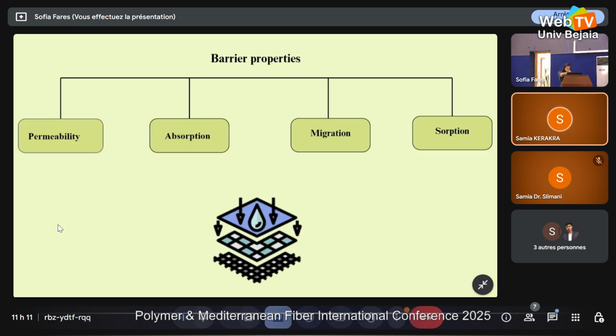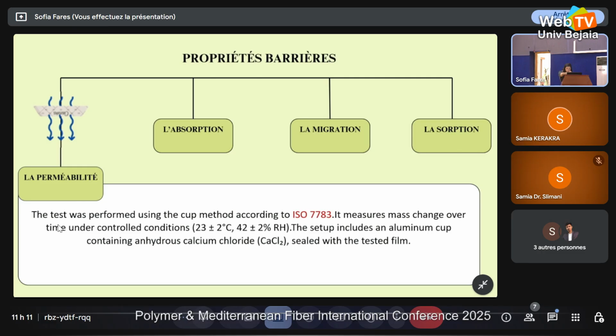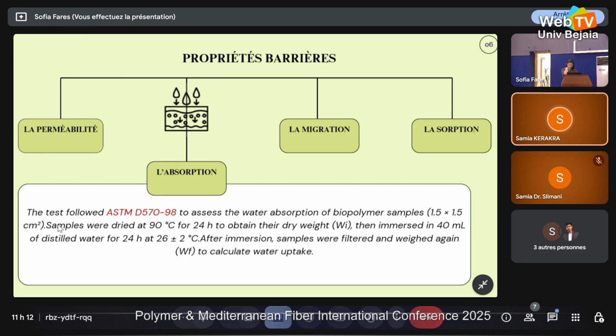So let's explain the main barrier properties introduced in this study. The first is permeability, absorption, migration, and sorption. Let's begin with the permeability, please. Our test was performed using the cup method according to ISO 7783, which measures mass change over time under controlled conditions like temperature and humidity, and this test is well known. The second one, absorption. The test followed ASTM D570 to assess the water absorption of biopolymer samples, and this one also is very well known.